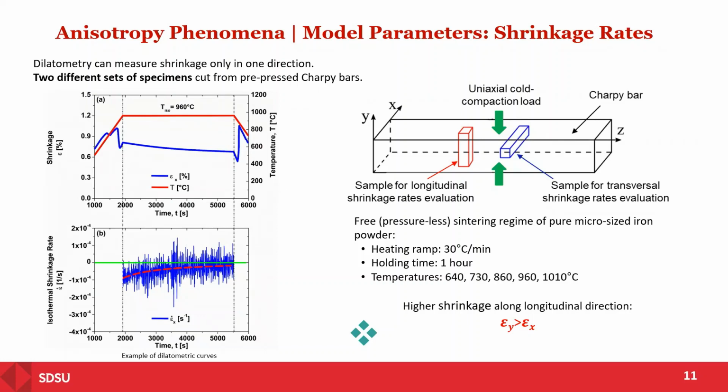Sorry, this might be a very simple question, but why do you even expect a shrinkage in the orthogonal direction? I mean, thinking of a normal material, you compress and it'll expand in the other direction, right? So what is making it shrink? Because it's in a die. So in the other direction, it's confined. Okay. But the pressure that you apply in this direction with respect to the other two directions is higher, because the other two directions get split. So it's direct that. And you can notice it also from those microstructural images, because the typical shape for metallic powder, even if sometimes irregular, is spherical. So if you get more concave shapes, it means that in one direction the particles have been deformed more than in the other two directions.